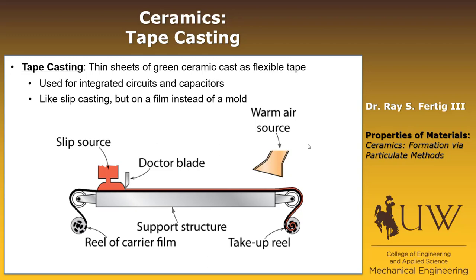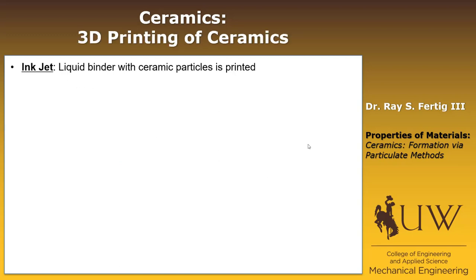A more cutting-edge topic is the 3D printing of ceramics. There are two classes I want to cover. The first is inkjet printing — shooting out an ink that's a liquid binder with ceramic particles embedded in it and printing layer by layer. You get a green ceramic part that still has to be fired, so the particles sinter together to form a final ceramic.